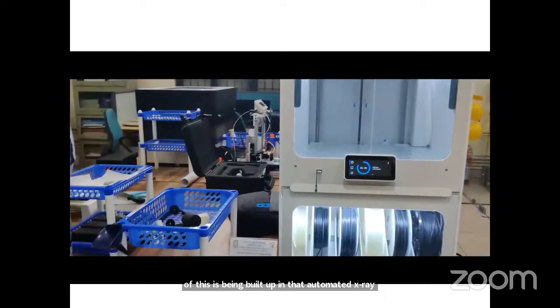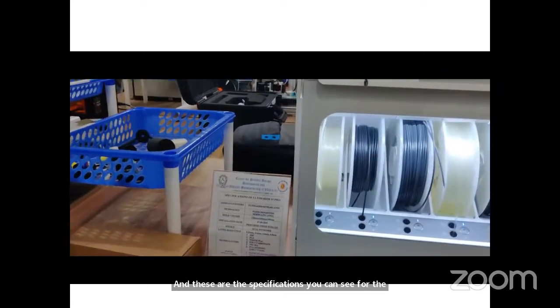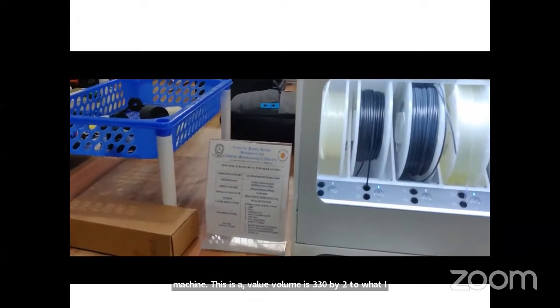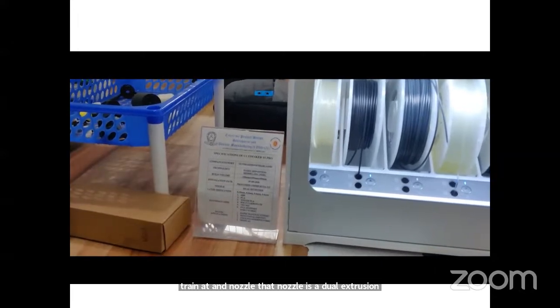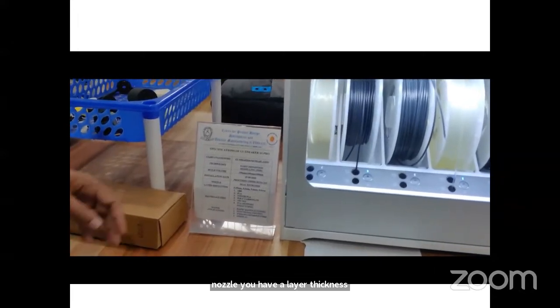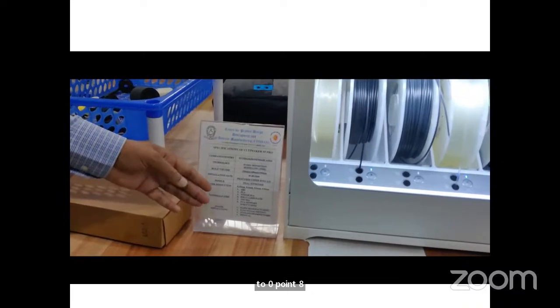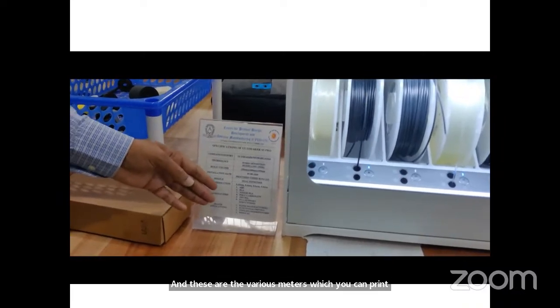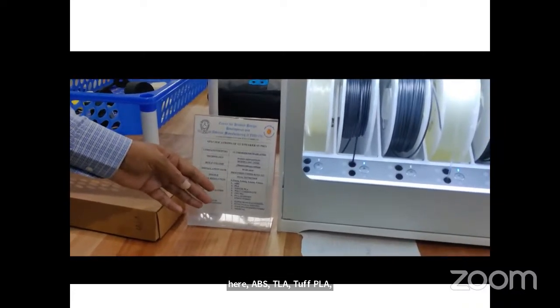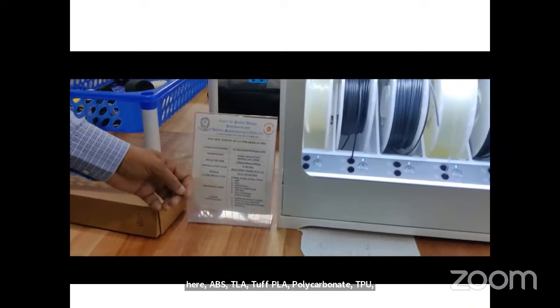The build volume is 330 by 240 by 300 mm, and the nozzle is a dual extrusion nozzle. You have a layer thickness from 0.25 mm to 0.8 mm, and these are the various materials you can print here: ABS, PLA, tough PLA, polycarbonate, TPU 95A, PVA for support structures, etc.